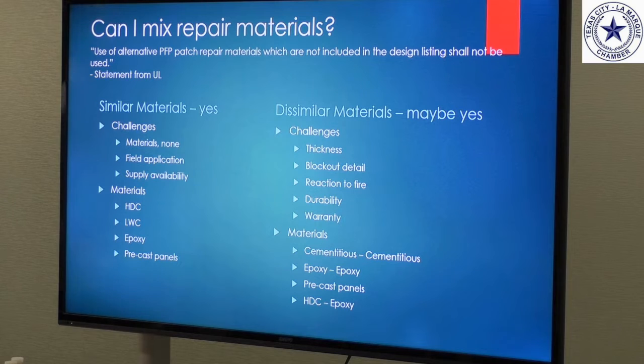There are multiple products you can choose from. Again, we have the high density concrete, lightweight cementitious, the epoxy, and one that's not known as much is the precast panels. So those are essentially panels that are created with epoxy intumescent product, and they're able to be assembled on the structure, kind of like putting Legos together. And that will allow you to replace the failing fireproofing and box out an area that needs to be protected. It's a very quick and cost-effective means to repair damaged areas.